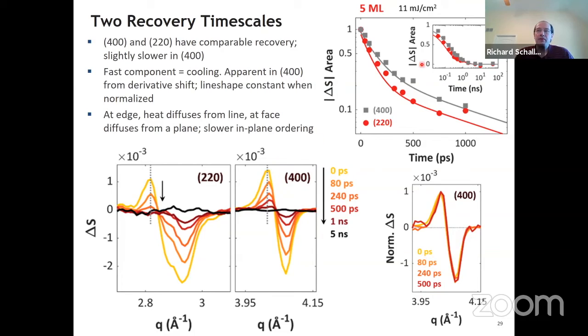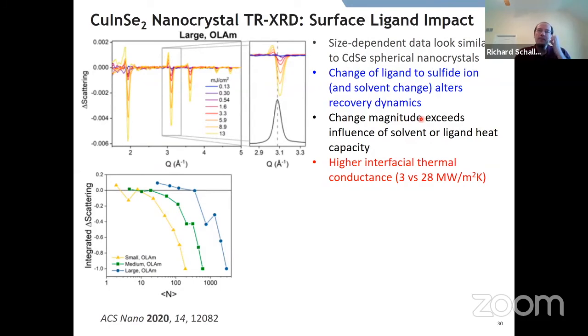And these systems also have these different dimensions. So if you're having heat leave from a large face of the crystal versus from a smaller face of it, that's something that can overall dominate what this recovery looks like. The crystallinity recovery is also something that looks asymmetric, in that sense of it taking a long time for these wiggled phases to go away. We've started to see some hints in other systems of dependence on what the ligand is on the surface of the particle.